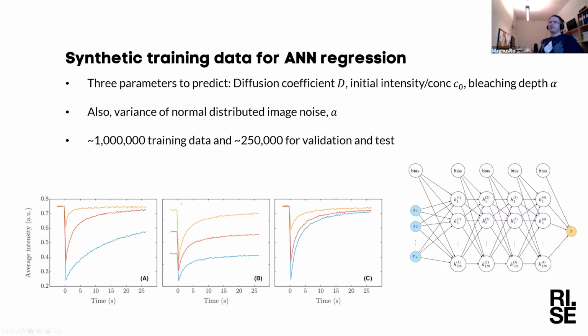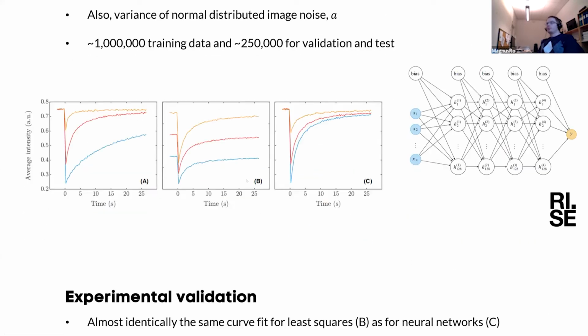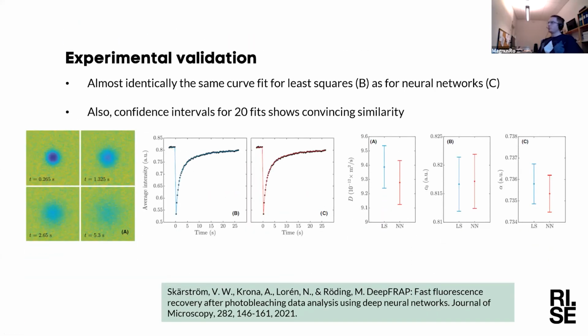So we generate synthetic data, curves like this. We vary the parameters, we vary the amount of noise, and we generate about 1 million of those and 250,000 for validation and test. And we plug it into a conventional fully connected neural network, like 4 layers, 128 nodes in each, nothing fancy. And we find out that we can actually train it to perform almost exactly the same as least squares does.